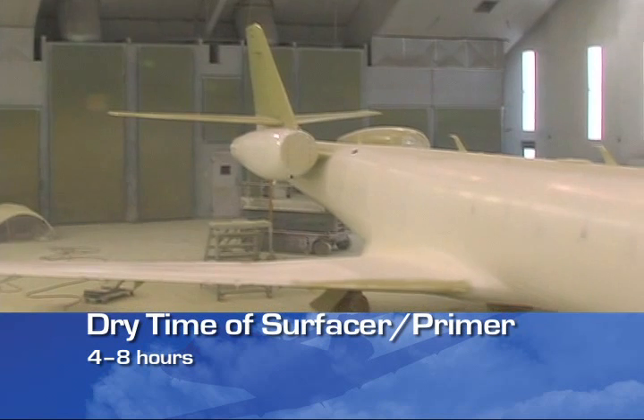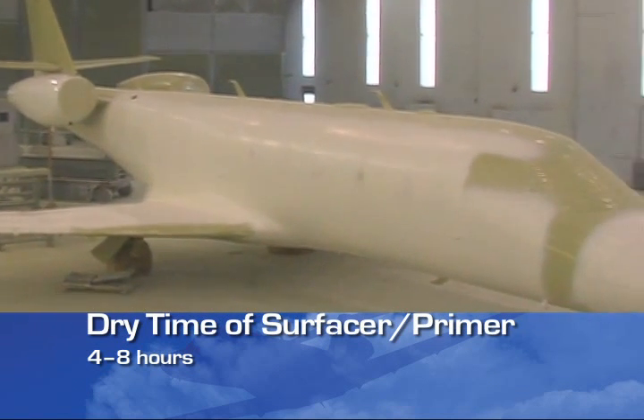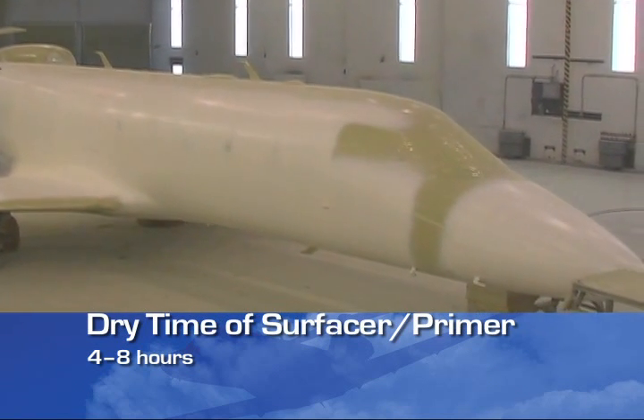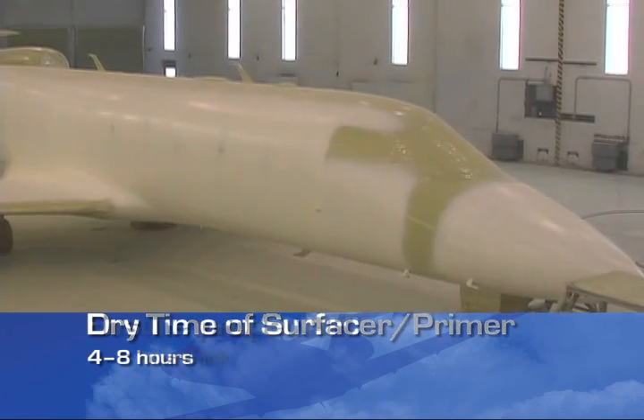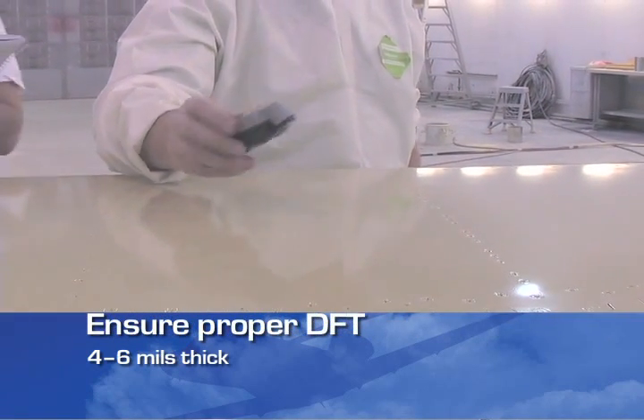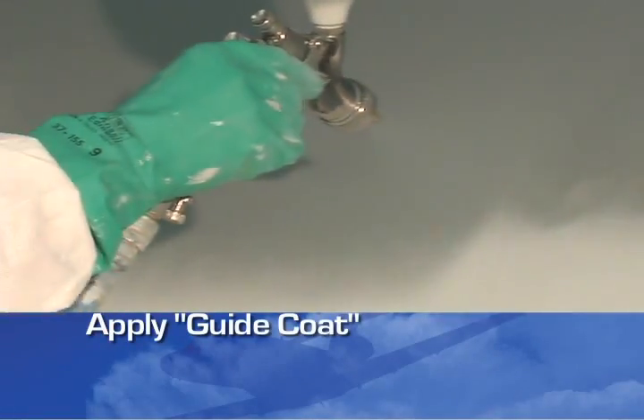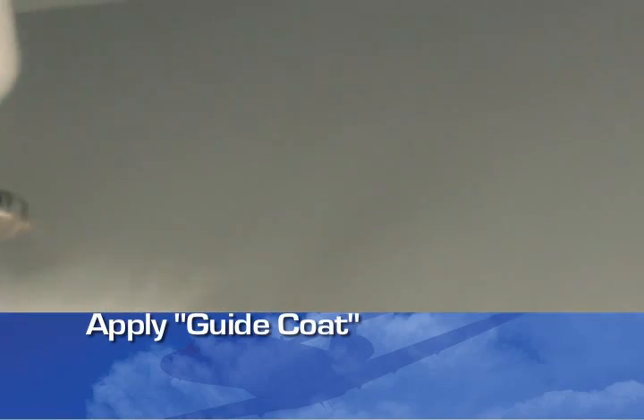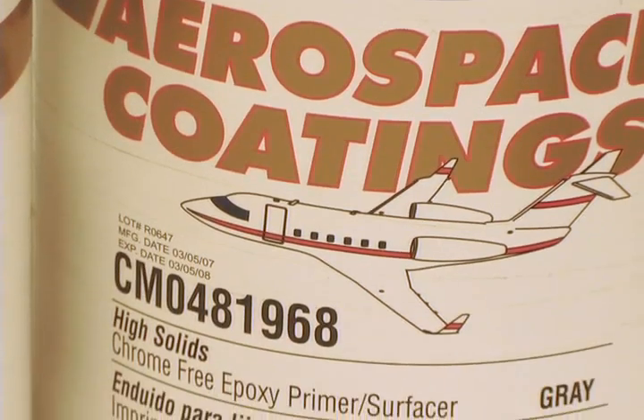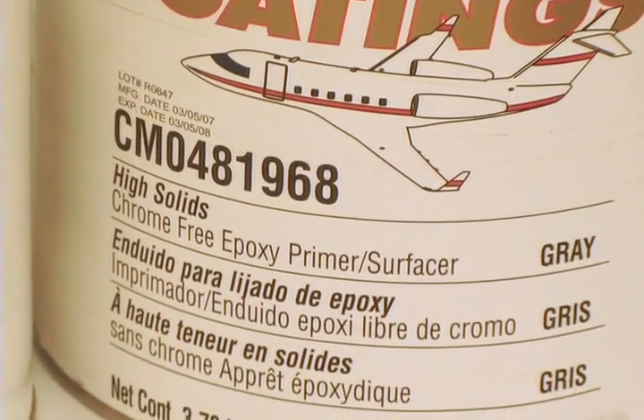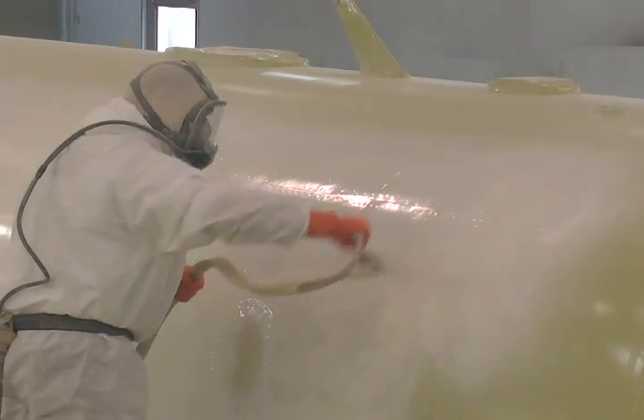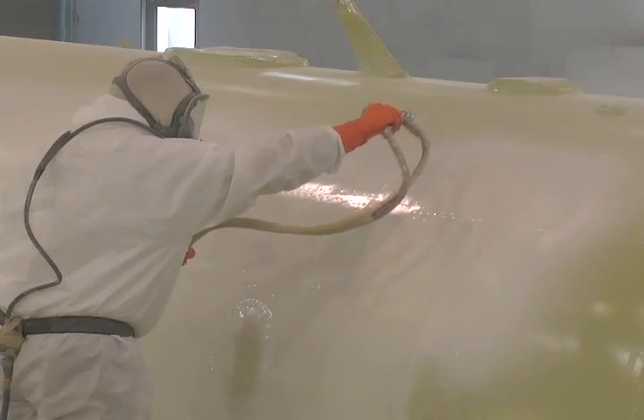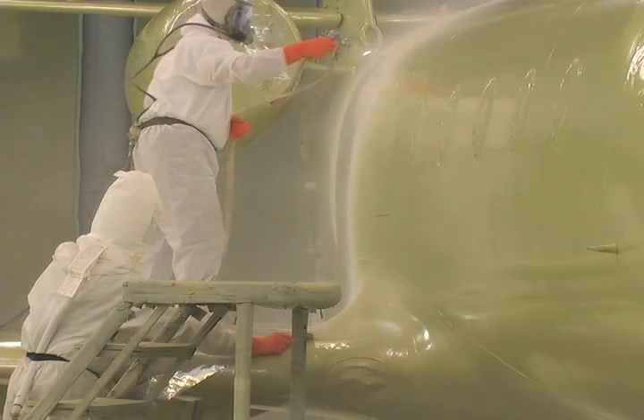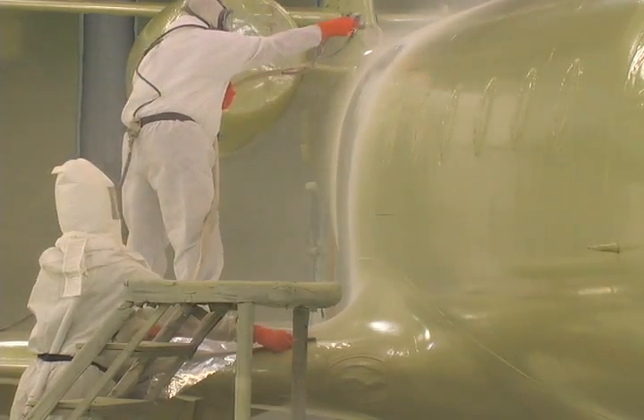This coating layer will require at least 4 to 8 hours of dry time at room temperature, depending on the thickness applied. After drying, the primer coat should be approximately 4 to 6 mils thick. Before sanding, apply a light black spray coat or guide coat to help identify high and low irregular surfaces. If Sherwin-Williams chrome-free primer is used, this step is not necessary because the chrome-free primer is specially formulated to change gloss and color as you sand it, acting as its own guide coat.